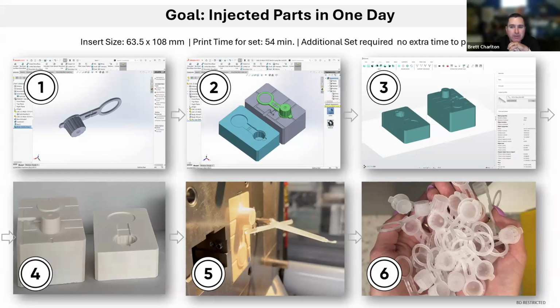to. So let me redefine it slightly to say that rapid tooling is the ability to remove or minimize the largest bottleneck in the process, the fabrication of the tooling components. Looking at the images here, the gap between image 3, the top right, and image 4 in the bottom left is usually significant. Depending on the complexity, the mold fabrication can take up to 6 weeks. I'm not suggesting that this mold would take anywhere near that long, but you certainly won't have the mold componentry available in 1 to 3 hours like you would with the Axtra system.